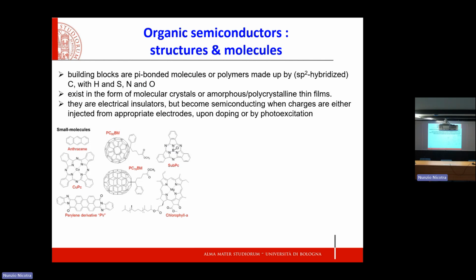So organic semiconductors are based on pi-bonded molecules, typically made up of carbon, sp2 hybridized, typically linked with hydrogen, sometimes with sulfur, nitrogen, and oxygen. So definitely many different structures that you can build, very varied, but these are the atoms that constitute these materials. They can be single crystal, amorphous, polycrystalline, and thin films. So as we do for atoms, we can play around with the final form. What is interesting is that they tend to be electrically insulating unless we induce motion of charges or injection of charges with electrodes, doping, or photoexcitation.